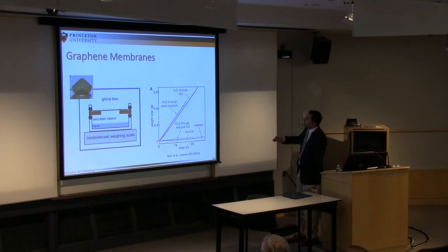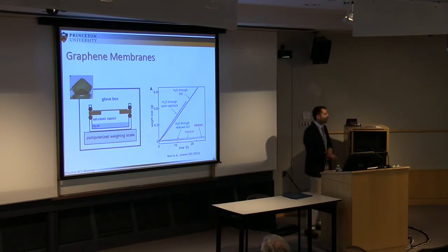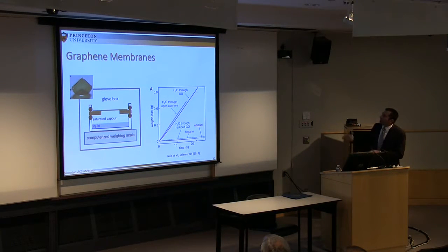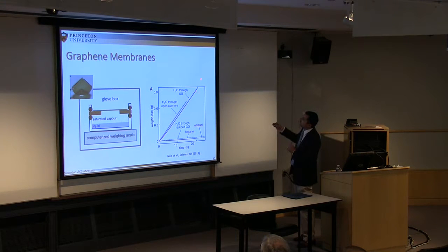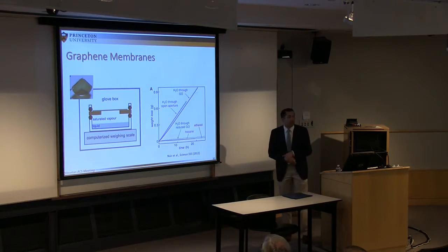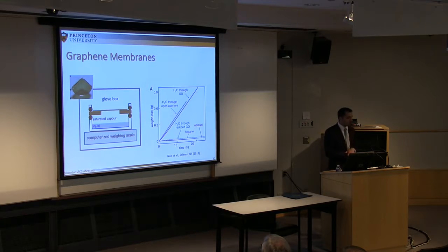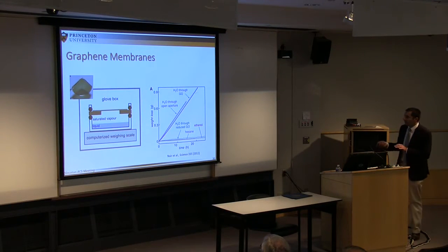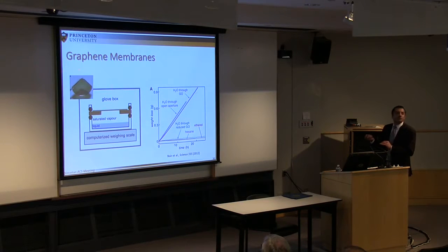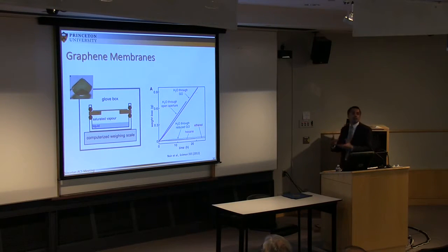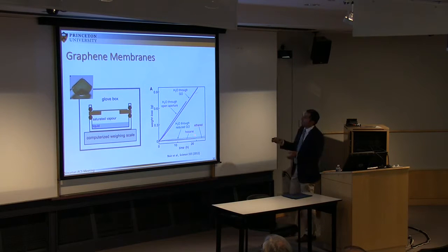When the aperture is open, water goes through at a very high rate. If they now use the graphene oxide as it is, directly after graphite oxidation, you also have a very high weight loss. So the membrane made out of graphene oxide is not a barrier. But what happens now if you reduce the material, thermally or chemically using hydrogen, for instance? You see that now water doesn't go through anymore.